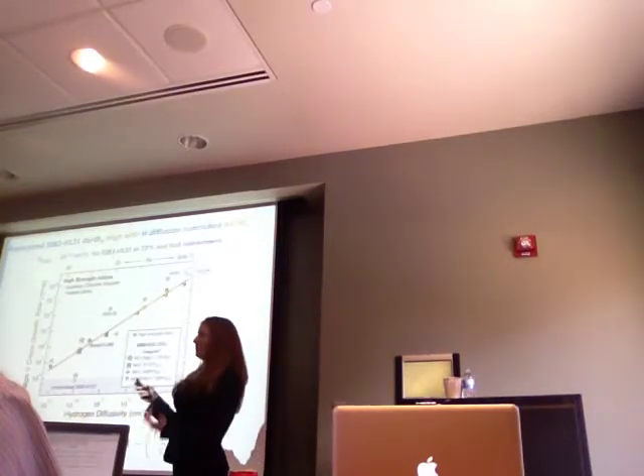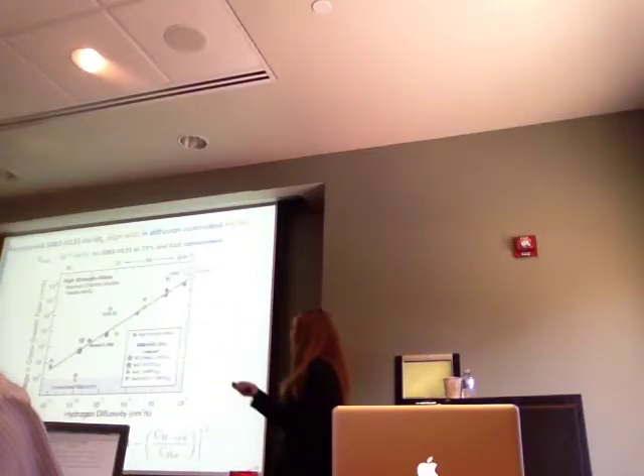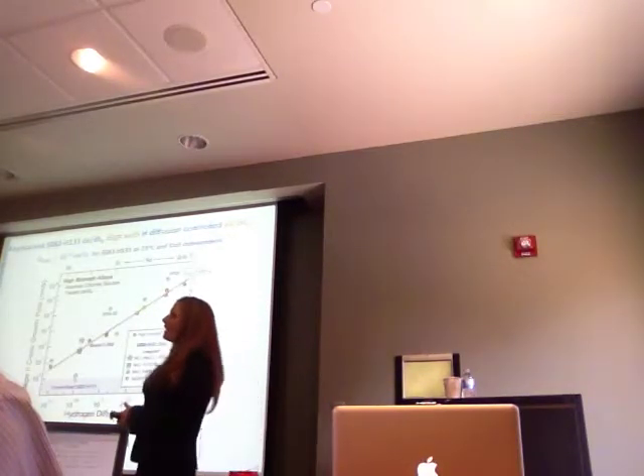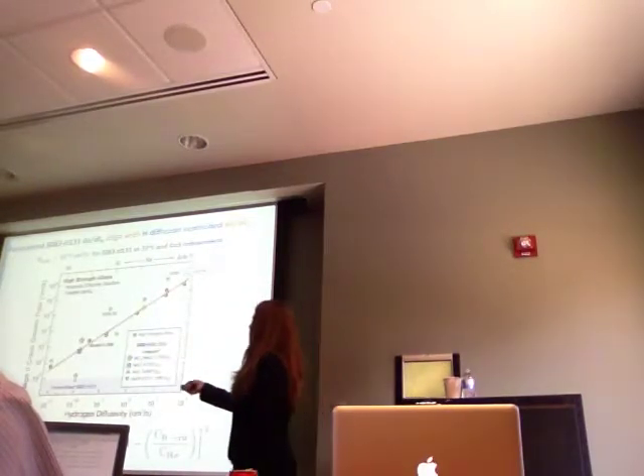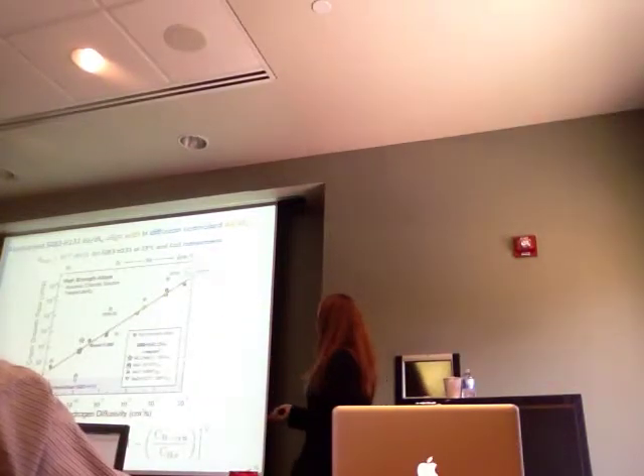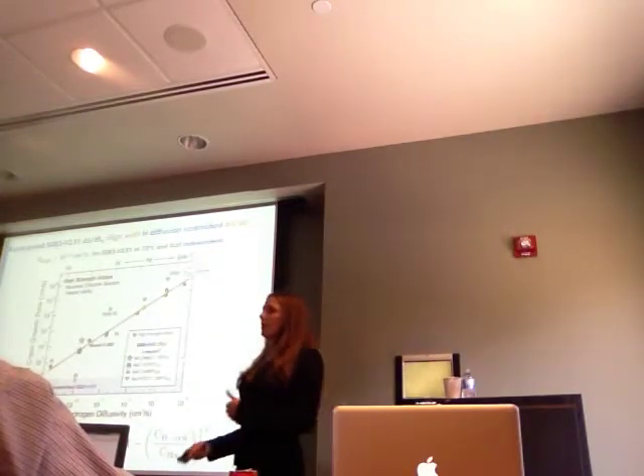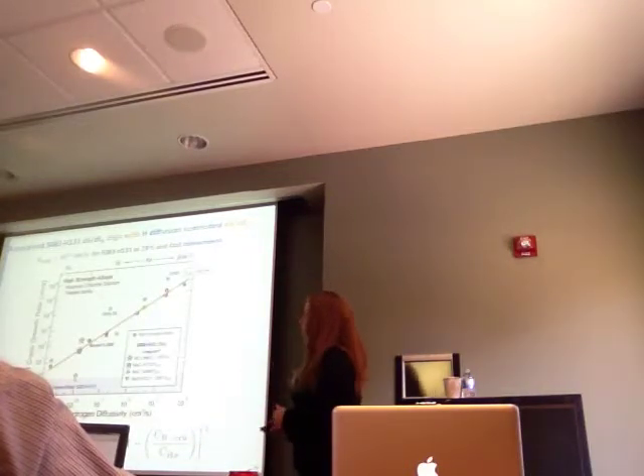Now what's interesting is our two very fast, susceptible crack growth rates lie right on this line. So that tells us that our crack growth rates are likely limited by hydrogen diffusion. When this falls below the line, that means that this term is taking over. Our hydrogen concentration at the fracture process zone is likely close to or below the critical concentration required for embrittlement.